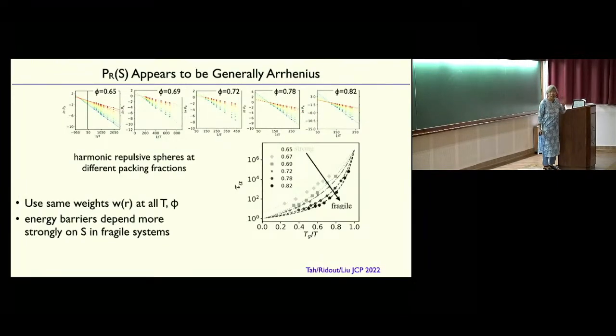This is data from Indrajit, where he looked at repulsive harmonic spheres, the potential for jamming, at different packing fractions. Ludovic Berthier showed long ago that you see very different fragilities as a function of packing fraction. Near the jamming transition, the log of relaxation time is quite linear in 1/temperature, so a well-defined energy barrier. But as you go to higher and higher density, it gets more and more super-Arrhenius.